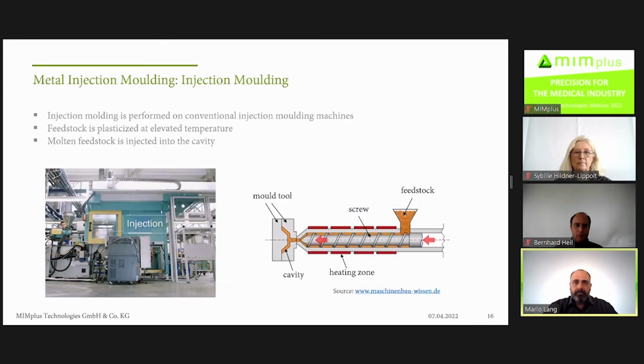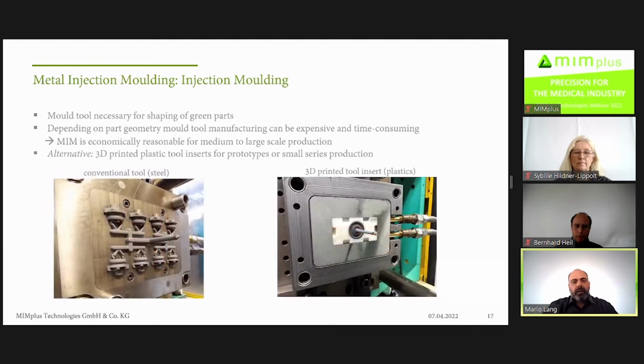And of course, the MIM process, so you do the metal injection molding of the feedstock in a conventional mold tool, and you plastify it, inject it, and so you get a part in the conventional way. It's quite a fast process compared to the AM processes. But it needs the mold, and so for low numbers, it's not a perfect process.